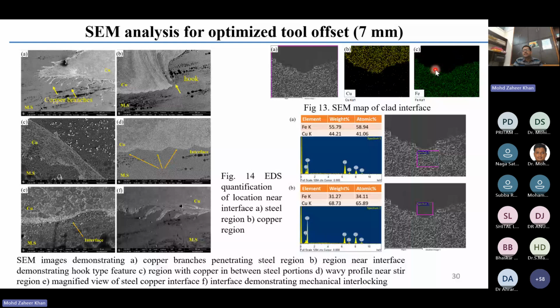Now, this is very significant because if we perform cladding by other processes like laser beam cladding or arc-based cladding processes, there is a very good amount of mixing of the substrate and the clad material. So if this type of mapped EDX is taken from a laser cladded specimen, we expect a good amount of iron in the cladded region and a good amount of copper in this region. So your top cladded layer will not be free of iron. That was what was desired in the case of cladding operation. We didn't want any substrate material. So in all those fusion welding or fusion cladding processes, this cannot be achieved. This I have already shown.